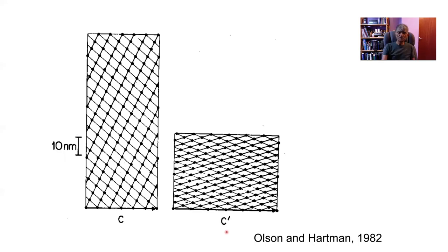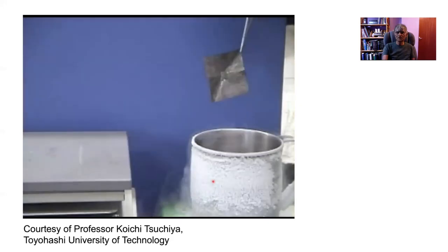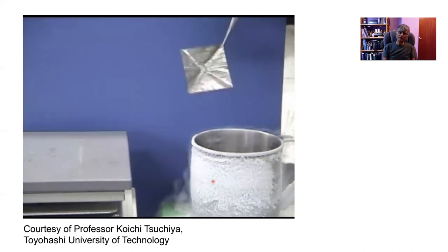Okay, so the point of this slide was to show you that there is a shape deformation associated with martensitic transformation, because obviously we have changed the pattern in which the atoms are arranged by a physical deformation rather than by breaking the bonds between the atoms and rearranging them into a new configuration. So the shape deformation is extremely important when it comes to martensitic transformations, and it dominates many of the features of the transformation.